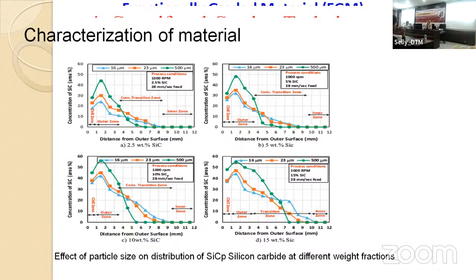For example, for the different phase ratios, can you see the effect of size on the distribution? The value is not important for us, but please see the behavior of this line. Please remember the thickness. The thickness of the hollow part is 12, so I can use the x-axis from 0 to 12. Attention to the concentrations of the silicon carbide in this area, the outer zone, for different added sample sizes. It's the inner zone. Yes, look at their behavior. And we take into consideration the transition zone. Yes, the transition zone is bigger for the 15 percent of silicon carbide when we add it.